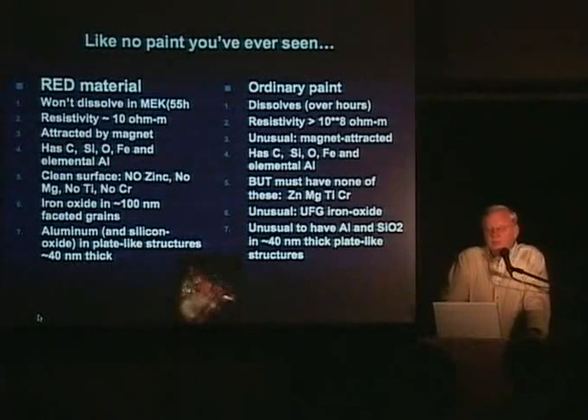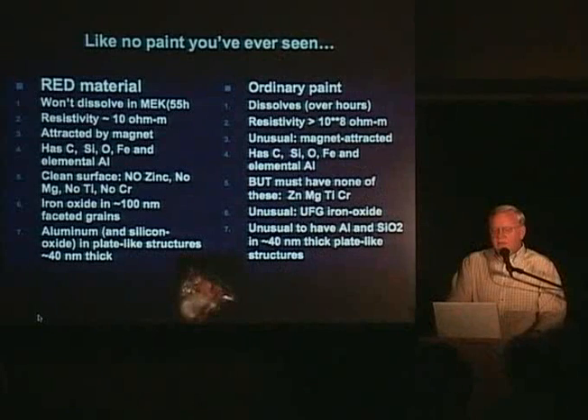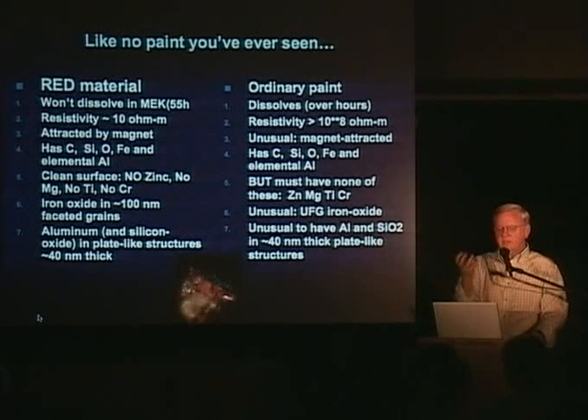This is like no paint you've ever seen before. Let's review quickly. The red material will not dissolve in MEK. This is after 55 hours. There's this hard chunk left. I've got a photo of it down at the bottom. It's highly porous, high in silicon. This skeletal silicon oxide matrix remains after long soaking, whereas ordinary paint dissolves.